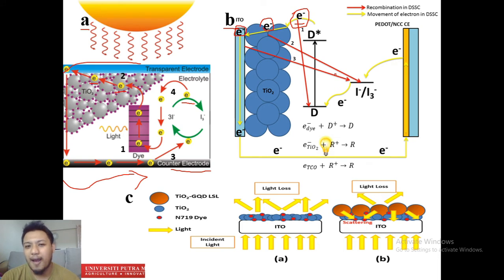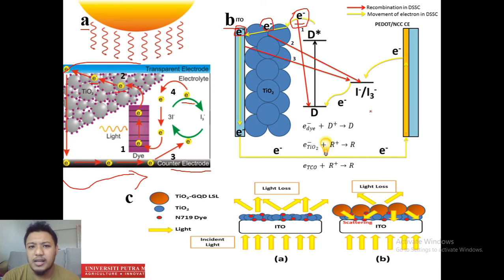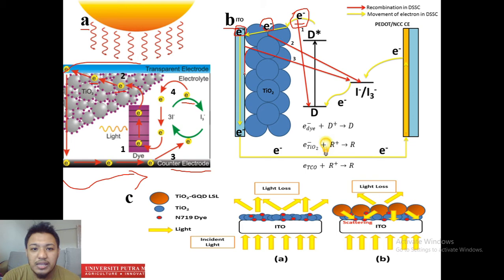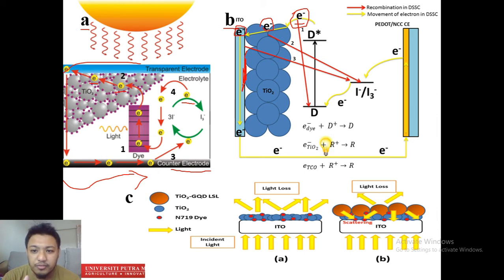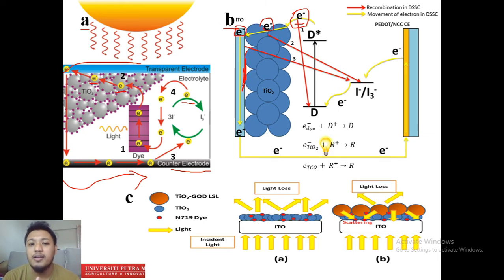There are many ways to prevent recombination. For example, using a good dye like N719 ruthenium-based dye, or using iodide/triiodide to reduce recombination. For the third type — recombination of the substrate electron with the redox electrolyte — a compact blocking layer is introduced between the substrate and the TiO₂ molecules. This prevents the substrate electrons from recombining with the electrolyte, and it is proven in papers that a blocking layer between the substrate and photo anode reduces recombination, as demonstrated by anodic peak current using cyclic voltammetry.